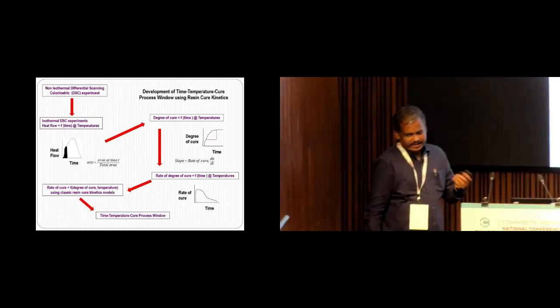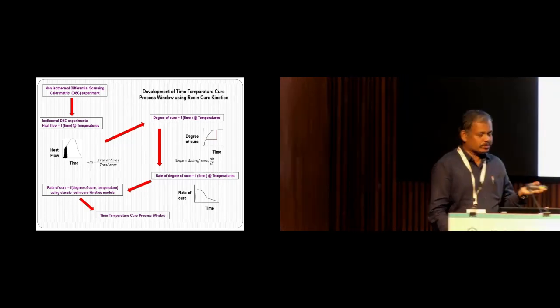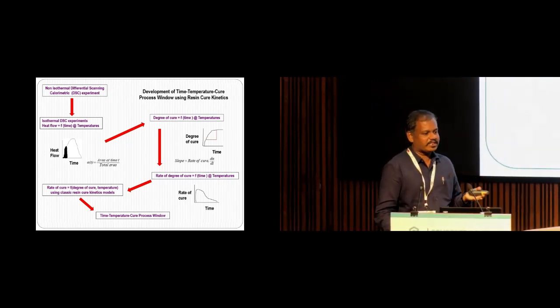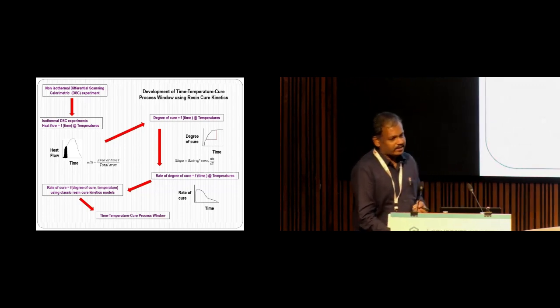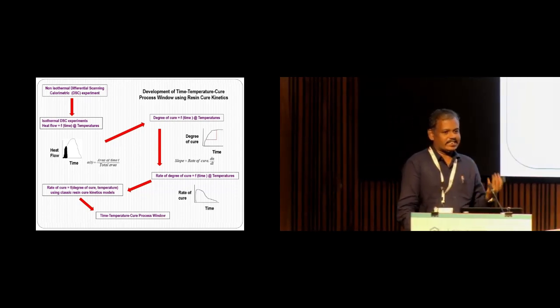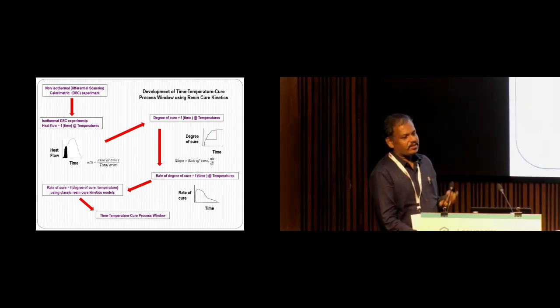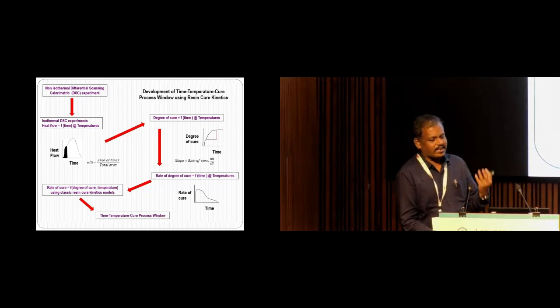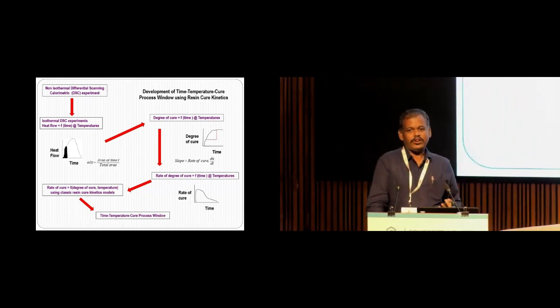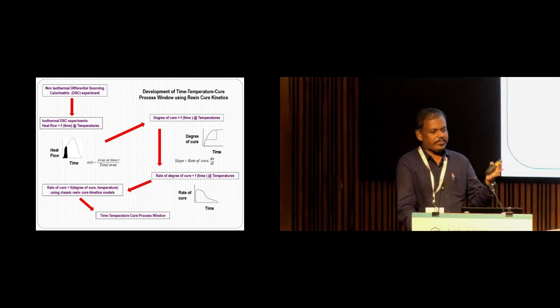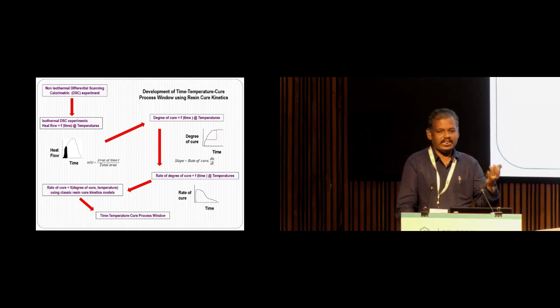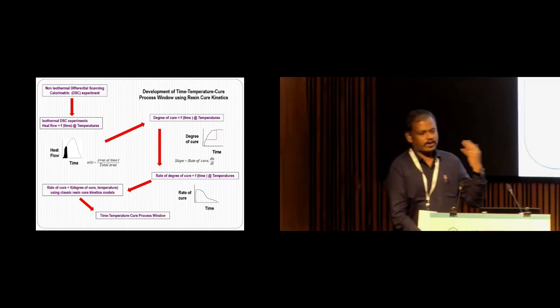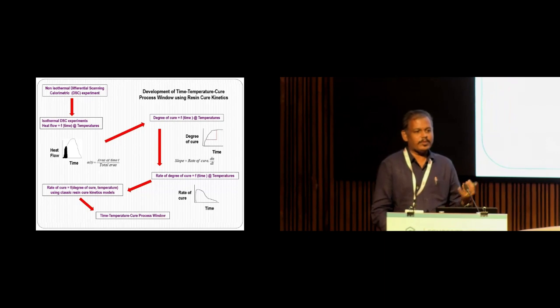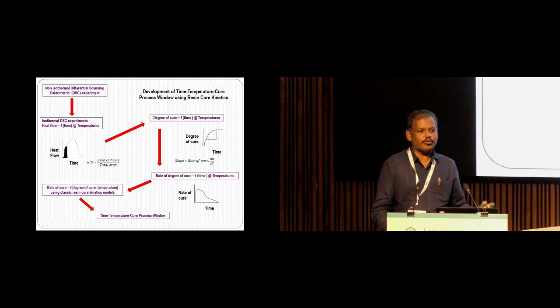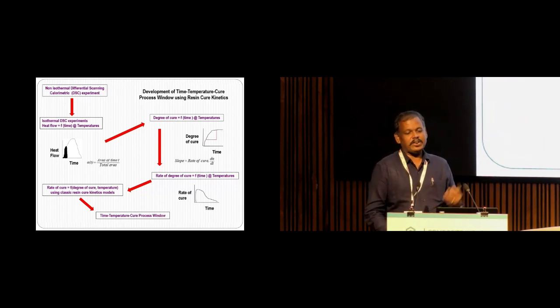So as I told earlier, I have used RTM6 resin because it is for aerospace composite laminate. When you go through any resin product data, the manufacturer will not give you any detail about the mechanism of curing. That means you are never going to get the time-temperature cure data. That means if I apply some kind of cure cycle, say 140 degrees for 5 hours, what may be the degree of cure? Generally we may not need this data because we tend to cure the composite laminates 100%.